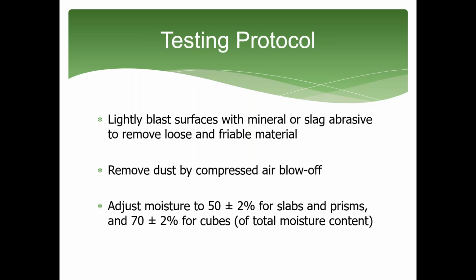Once the specimens are fabricated, the surfaces are lightly blasted to remove loose or friable material. The samples are then blown off with clean compressed air, and the moisture content is adjusted to 50% for slabs and prisms and 70% for cubes.